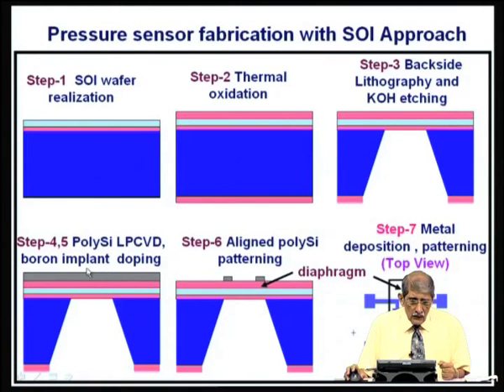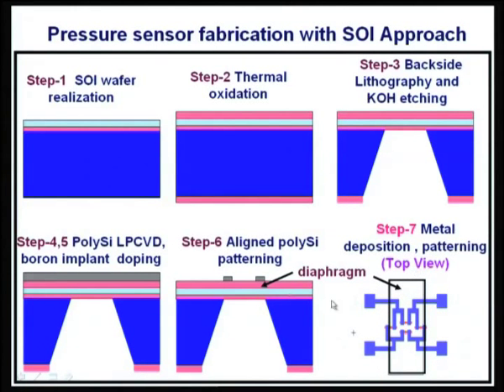Okay. Now, you pattern this polysilicon by means of lithography. Remember, you want to remove the polysilicon from everywhere except in the 4 red color regions here. If this is the membrane, looking at the top view, this is the region where you want to retain it. I have shown the cross section here, so I have shown only 2 here. There are 4. In the cross section, you will see only 2.